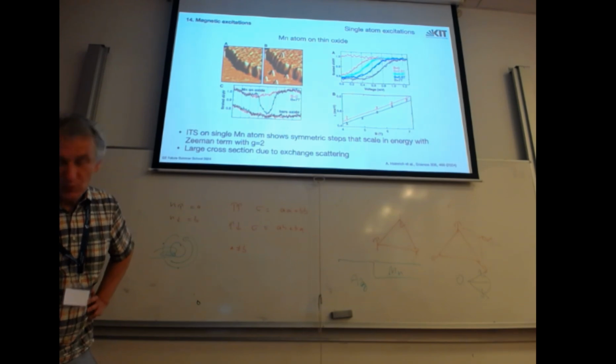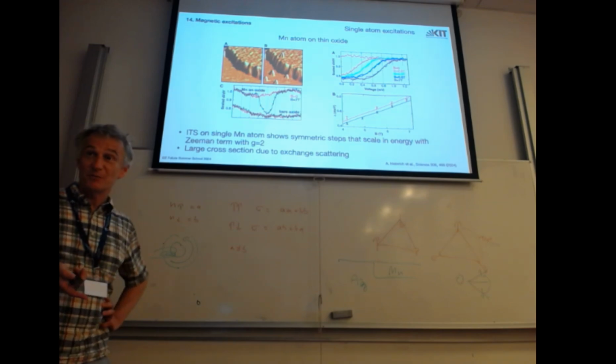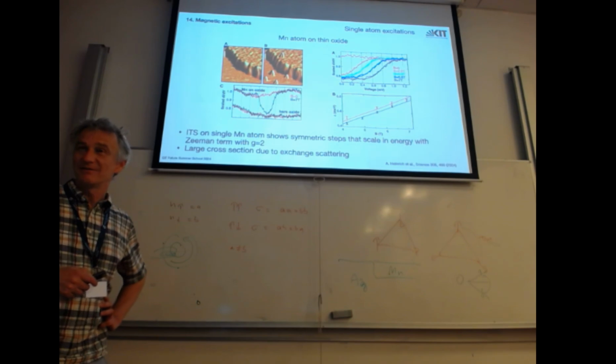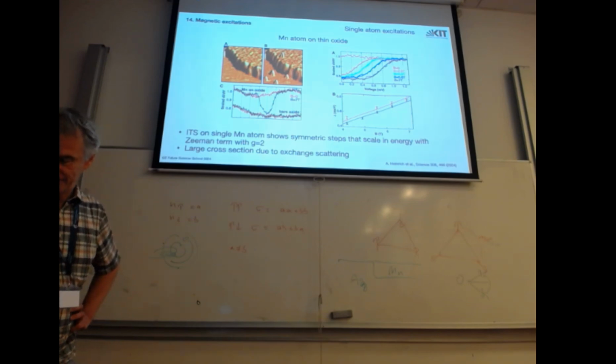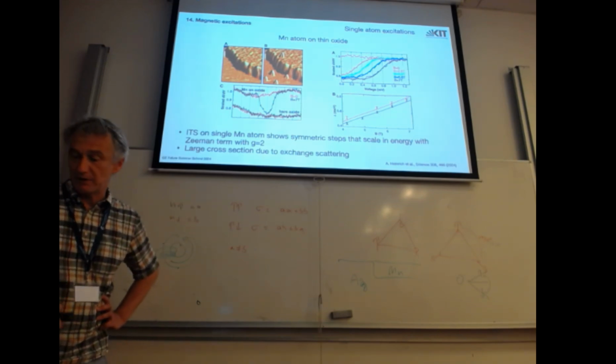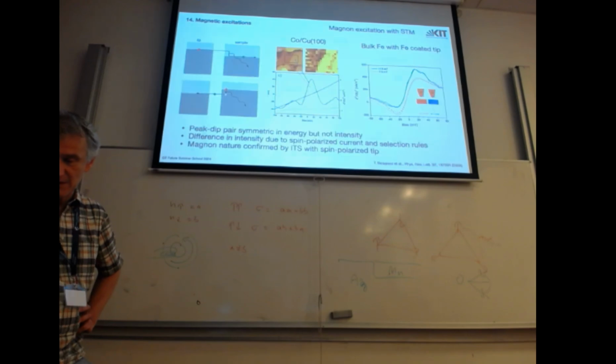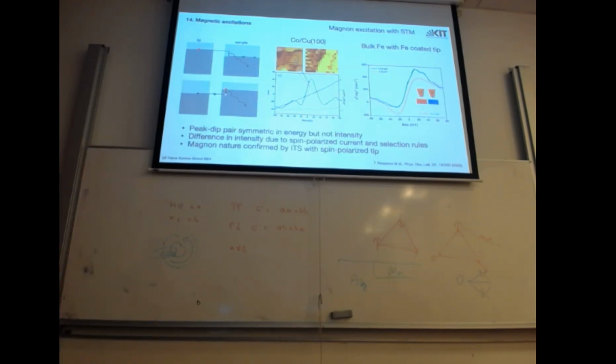So we can excite the spin of a system, in this case against the Zeeman energy, by a spin flip event. And it's just like a step up in the conductance, like it's inelastic energy that we transfer to the system. So maybe clearer in this picture, we come with a minority electron, it's scattered to a majority electron. This one will leave the sample on the backside, and we reduce the magnetization by 1 h bar from the emission of a magnon. So this is tunneling into the system. But we can also do the opposite, tunneling out of the system. If we take out a majority electron and a minority electron creates a spin flip here, you also can create a magnon.